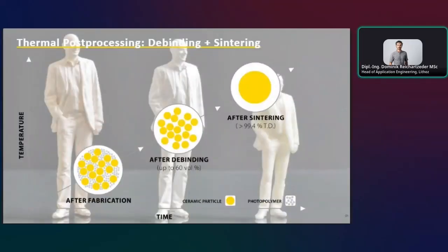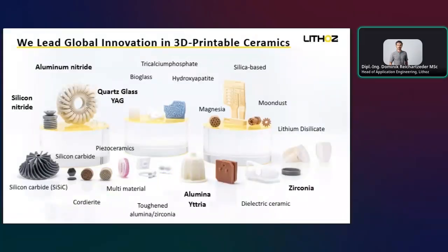After printing, the part needs to be thermally treated. At first, the polymer, which is still in the green body, needs to be decomposed and removed out of the part. This step is called debinding. After this step, the part only consists of packed ceramic particles. In the second phase, the part needs to be sintered to reach a fully dense part having the desired ceramic properties. This sintering is done at high temperatures below the melting point of the material. During this process, the part shrinks, which can be seen in the picture here of our CEO, Johannes Homa, shrinking about 20% in size. So this was the core technology.